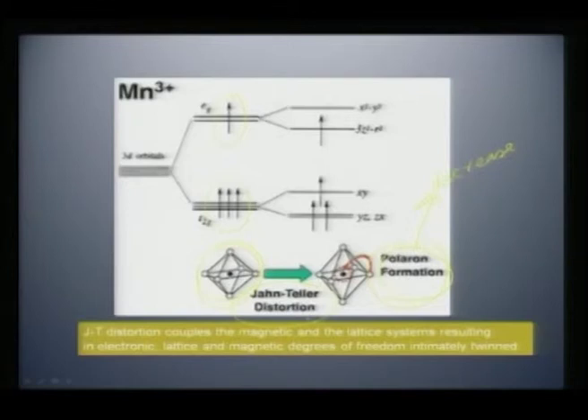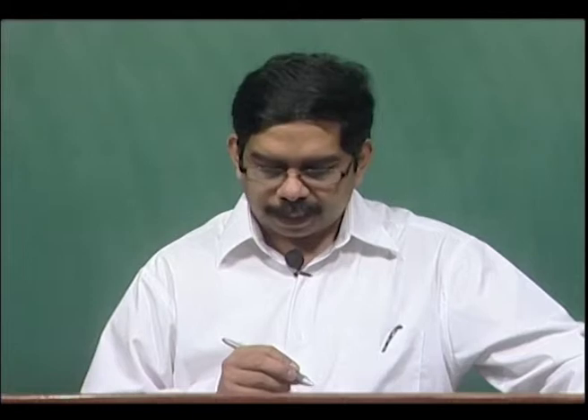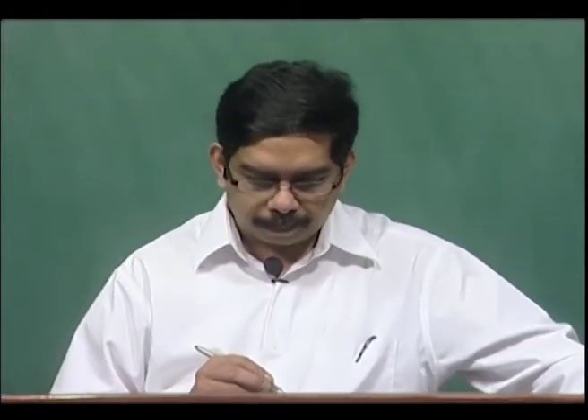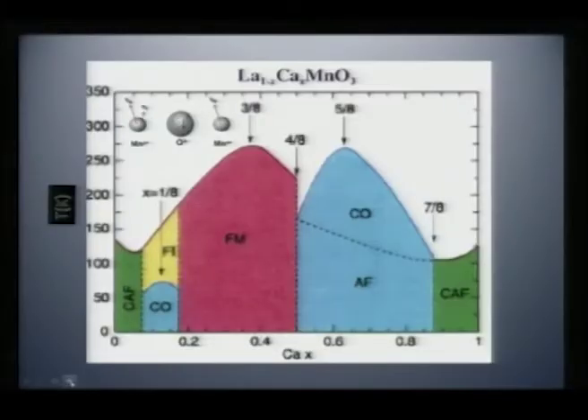Both are operating in this small unit cell, and therefore we can sum up to say that the Jahn-Teller distortion couples the magnetic and the lattice systems, resulting in electronic, lattice and magnetic degrees of freedom intimately twinned. Therefore, this cooperative effect present in the unit cell of manganites makes this a more interesting system to study.